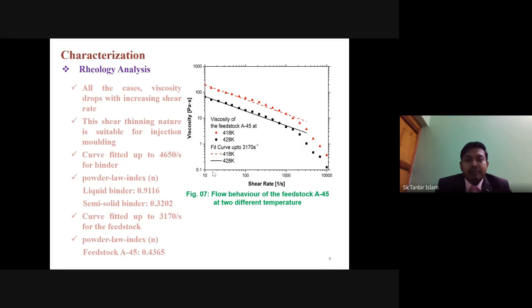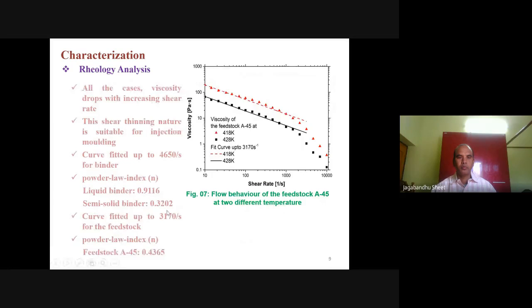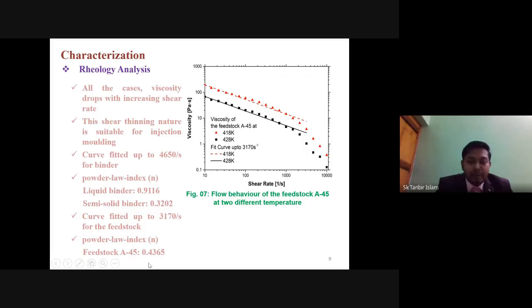A similar kind of experiment was carried out for the feedstock, and we found a shear thinning behavior here also, which is favorable for the injection molding process. From the model we used earlier, the modified Cross model, we found the power law index is 0.91 for the liquid binder, 0.32 for the semi-solid binder, and 0.43 for our feedstock. There is a significant difference between the liquid binder and the semi-solid binder, which means the semi-solid binder is highly dependent on shear.